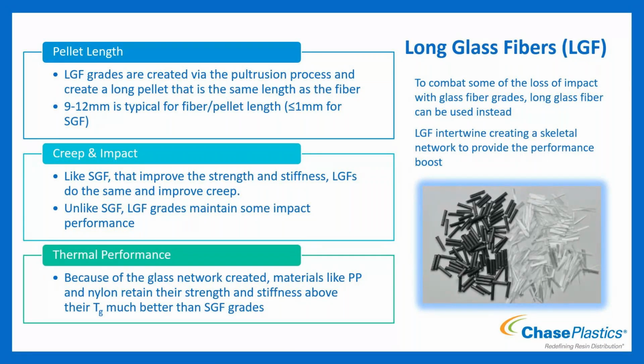It creates a long pellet. If you've never run long glass fiber materials, the pellets are long compared to the more standard round pellets you're used to running. The whole length of the pellet is the whole length of the fiber as well, and that's why they're longer. 9 to 12 millimeters, depending on the base material and who's making it, is standard for the length of long glass fiber, compared to about 1 millimeter for short glass fiber—quite a big difference. If you've never run it and then you buy it, you might wonder why the pellets are huge—that's because they're the length of the fiber itself.